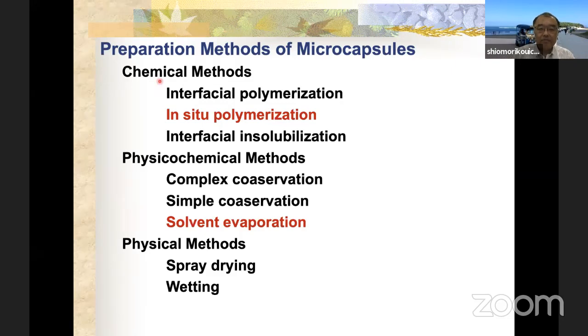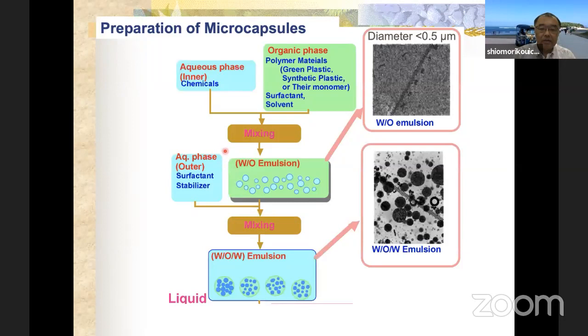So, a typical preparation procedure using this method is shown here. Firstly, we make a W/O emulsion. The W/O emulsion is prepared by mixing immiscible solutions, an aqueous phase and an organic phase, like this. After preparation of the W/O emulsion, the W/O emulsion was redispersed in aqueous solution.